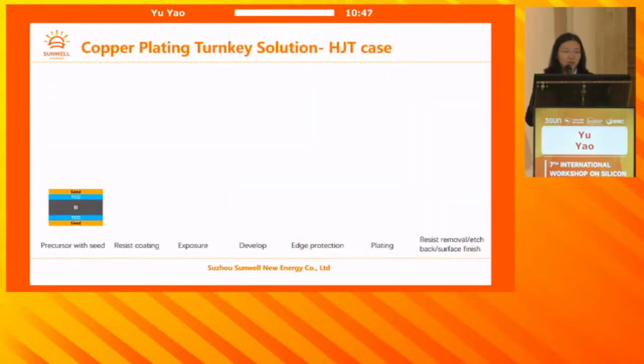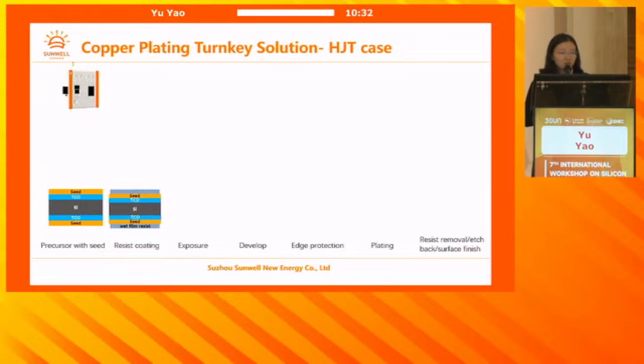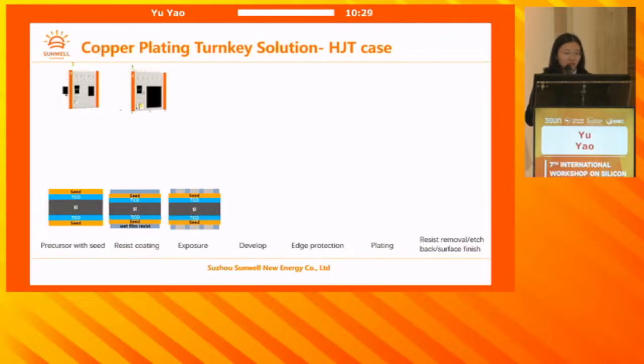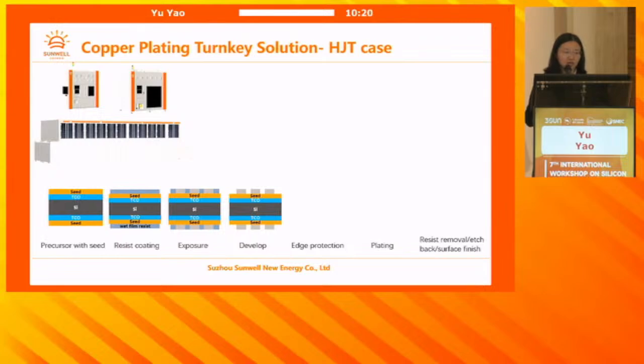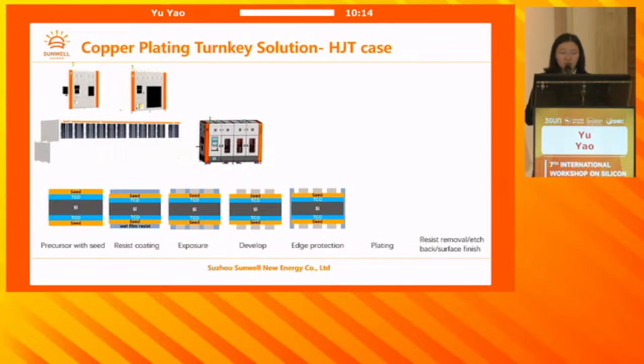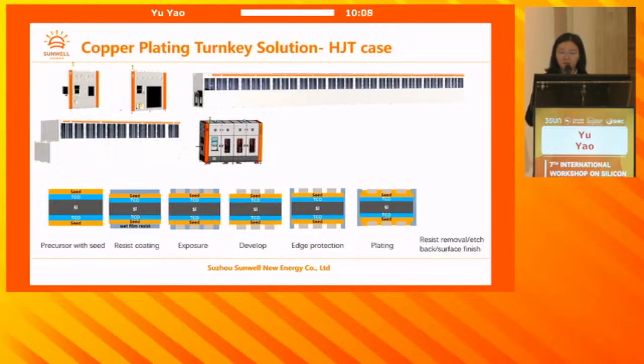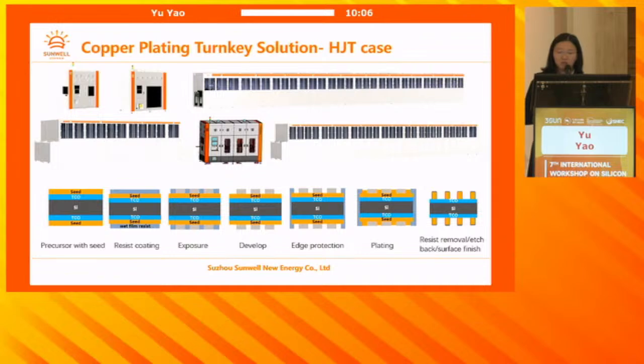So going back to the copper plating turnkey solution for heterojunction cells, our process starts with the seed layer on both sides. We have developed the equipment, process, and materials necessary for coating, firstly, the resist on both sides, and doing light exposure to define where the openings and the masks should be. A wet chemistry inline machine makes the openings, and there is also edge protection equipment and material to protect the edges. Then we do the plating and finish with the resist removal, etch back, and surface finish.